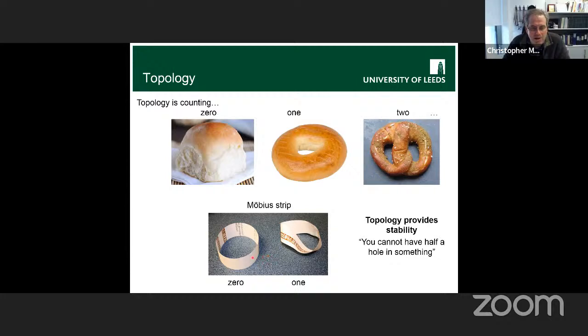And so I could say, well, now I can store a bit of digital data in this loop, if I call this a 0 and this a 1, by looking at the twist. Once I've done that, I can treat this quite roughly. I can scrunch it up into a ball, throw it in a bag with some others, and get it out. And if you get it out again, as long as you can still see whether there's a twist or not, you can recover your data in spite of all those other things that have happened along the way. And so this is why it's attractive to think of using Skyrmions in this way.